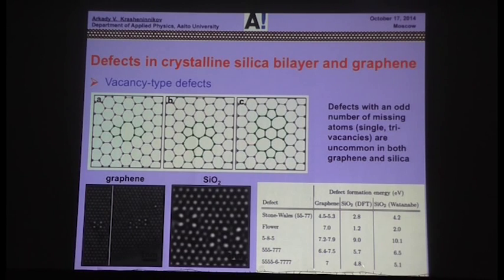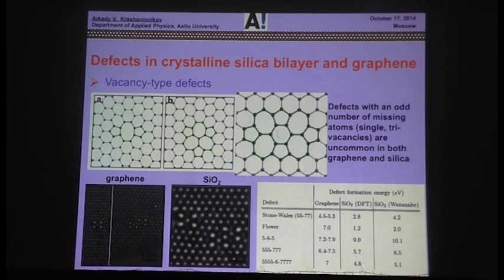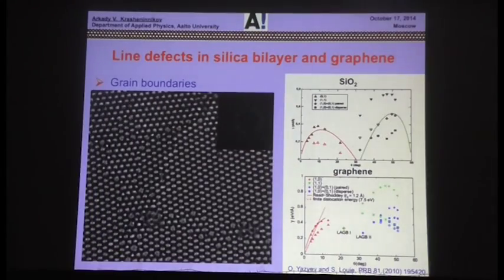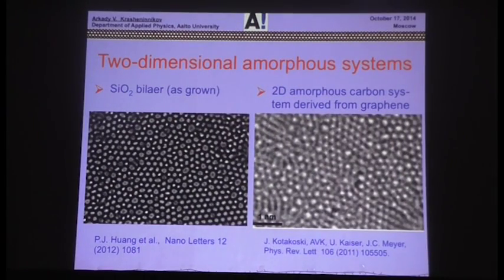The reconstructed divacancy I mentioned already today is the butterfly defect, which is the same, and I just rotated it again by 90 degrees. And these are examples in graphene and in SiO2. Also, the energetics of grain boundaries has something in common, even though it's still a bit questionable there. And finally, both silica bilayer and graphene can be amorphous. Amorphous graphene is something really special that you can make using an electron beam under very special conditions. But anyway, it's pretty much a random 2D structure, or almost random. There is still short-range order in there. So lots in common between the two systems.